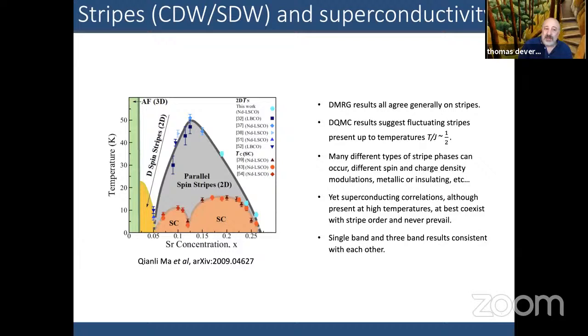So the bottom line in terms of stripes and superconductivity, I think that there are a lot of results now. We'll all generally agree on stripes being a very dominant feature in the low energy behavior of the Hubbard model, in the ground state as well as at finite temperatures, at least when temperatures get on the scale of about J, where spin stripes seem to persist up to that temperature. And there are many different types of stripe phases that can occur with different modulations, which seem to be controlled largely by T prime as the dominant control factor.